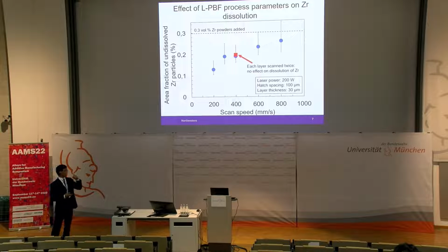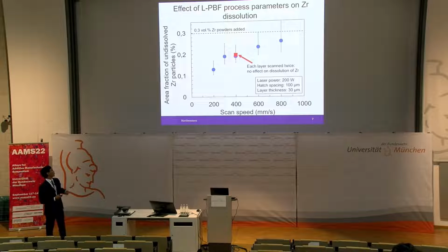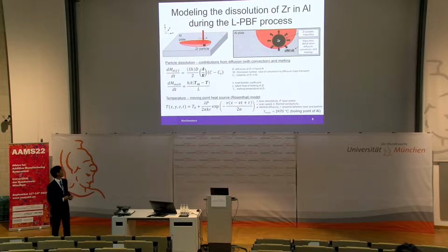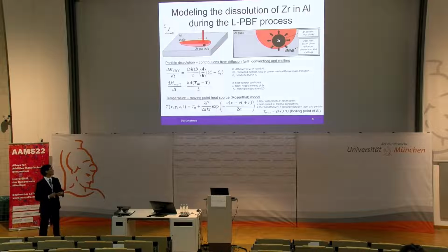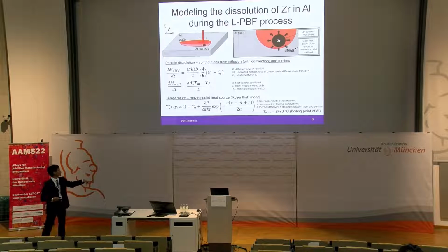But at the end of these experiments, we see that we still have quite a bit of undissolved zirconium particles. So we strive to understand the effect of these parameters further and understand what we could do to further improve the homogeneity by modeling. Let's consider a simple model. We consider a spherical zirconium particle immersed in the aluminum powder bed, and then measure how much the zirconium particle dissolves as the laser passes over it. We do this by numerical modeling.